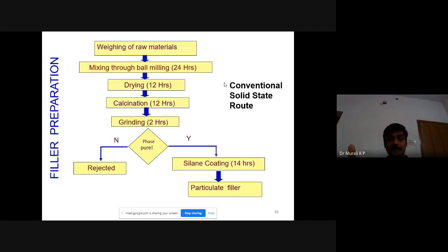According to the final composition, take the stoichiometric ratio of the raw materials, mix it, dry it, then calcine it at the required temperature, then grind, then do XRD, to see whether the phase has been formed. Otherwise, take it to high temperature, grind and take to high temperature again. We usually follow the conventional solid state route. And once the XRD shows the phase purity, we can take it for dispersing it in the polymer matrix. So generally the solid state route is followed for the synthesis of our ceramic filler.